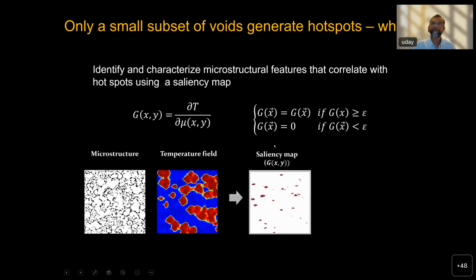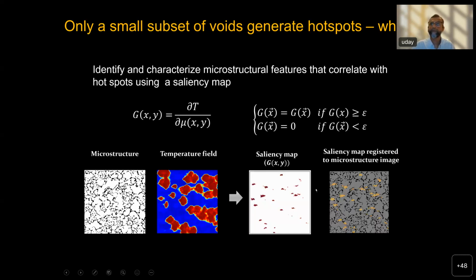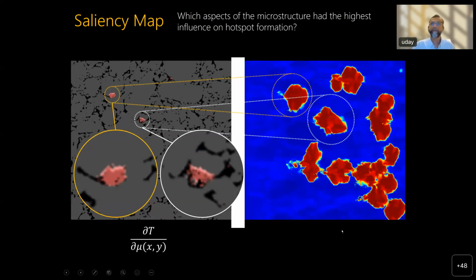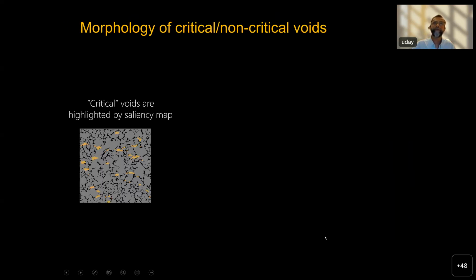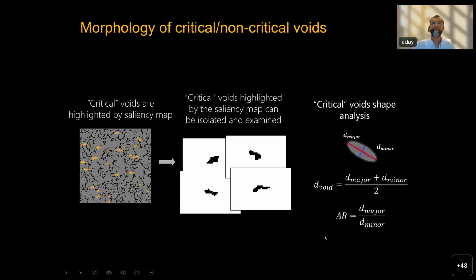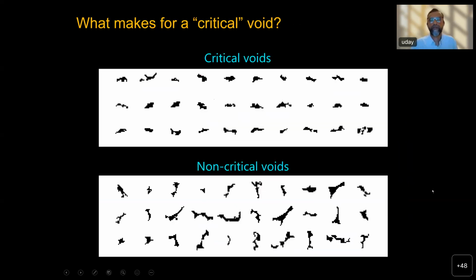And so if we threshold the saliency map field, we find that the saliency map tells us which voids went critical and formed hotspots. And so we can superpose this on the microstructure and we can examine these voids that cause the hotspots. As you can see, the vast majority of voids fail to produce hotspots. So then we're asking what is special about these critical voids? And we zoom in there and we try to correlate the morphology information with the sensitivity information. And what we find by doing this analysis matches the physics that we had earlier learned in various other works.